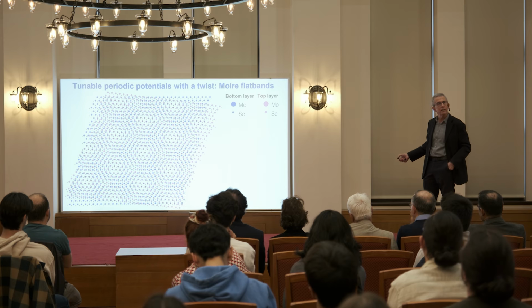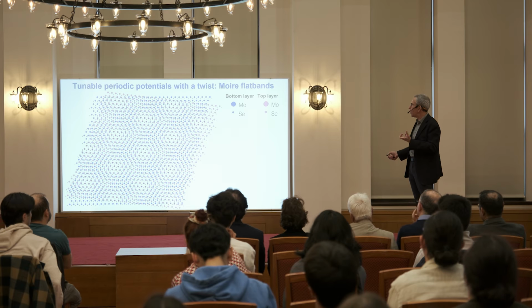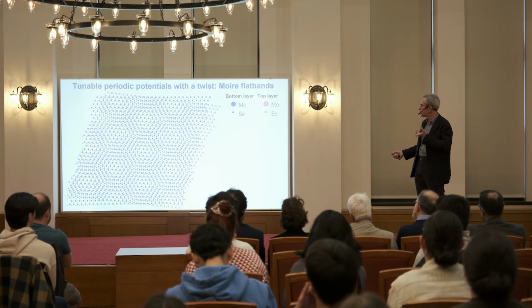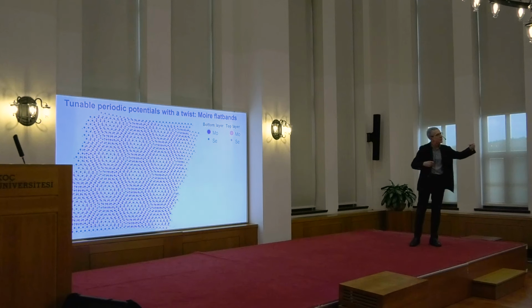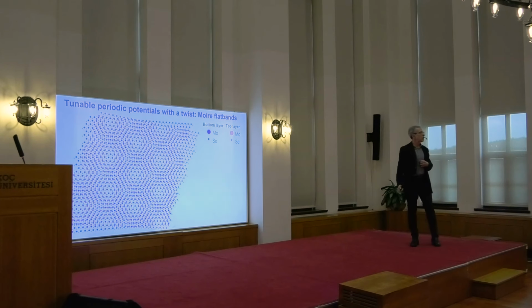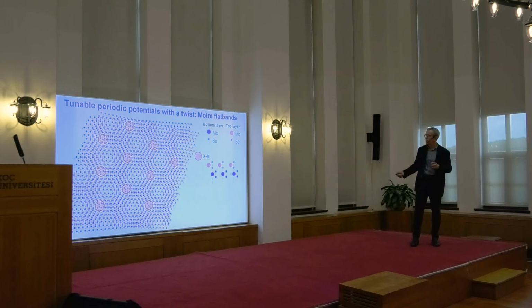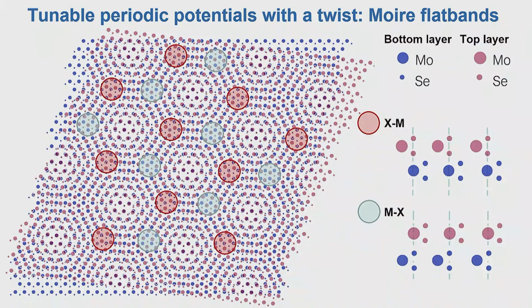And this superlattice means that electrons now in this bilayer material, twisted bilayer material, are going to be subject to a periodic potential on a longer length scale. Okay? And there are some special sites, high symmetry sites, where let's say the chalcogen atom sits on metal, or metal atom sits on chalcogen, or metal atoms sitting on metal atoms, and these actually create the potential variation within this unit cell. So the unit cell will be as you see here.